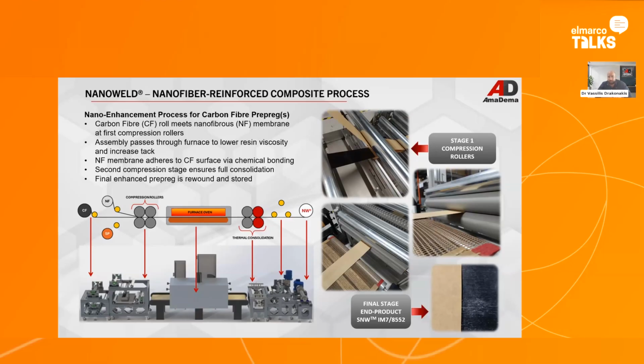So basically, carbon fiber rolls meet the nanofibrous membrane that has been taken out from the electrospinning system. The assembly passes through the furnace to lower the resin viscosity and increase the tackiness, and the nanofiber membrane adheres to the carbon fiber surface via chemical bonding. Then we have a second compression stage that ensures the full consolidation, and eventually the enhanced prepreg is rewound and stored.